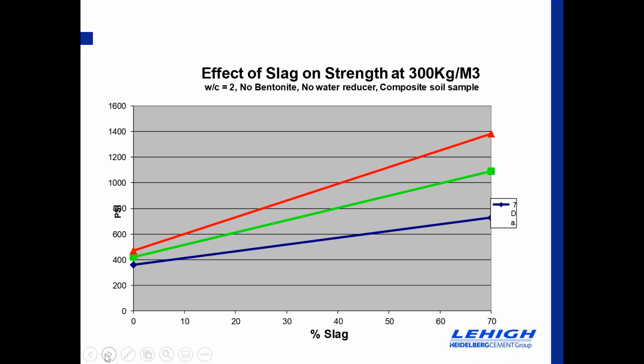So that was 100% Portland cement. Then we tested 35, 50, and 70. We ran it up to 70 because this was also a DOT project, and 70% happened to be where their specification allowed us to use up to 70%. So we didn't want to go above that, though, as I said in the earlier slides, in this particular application, 80 and 85% is also used quite often.